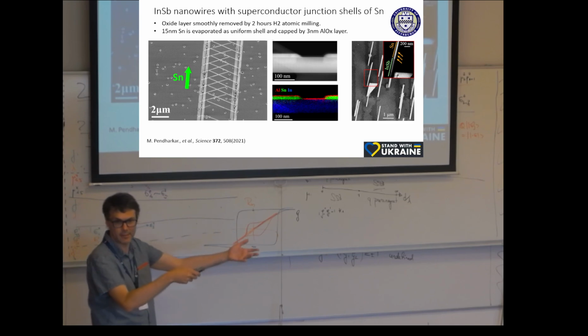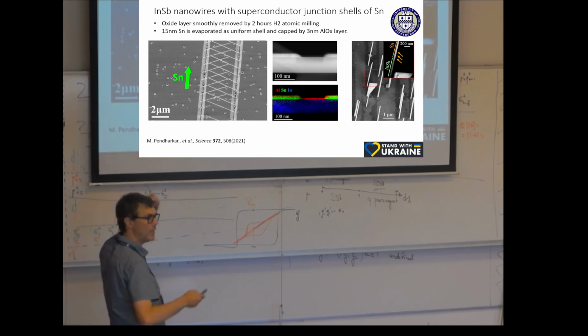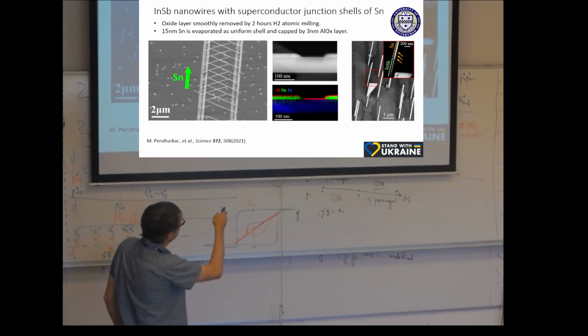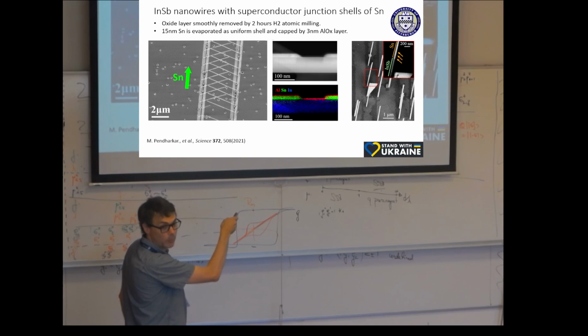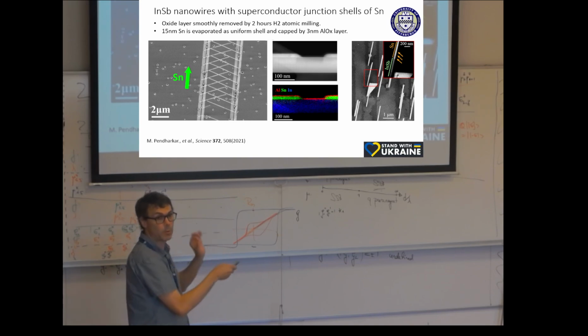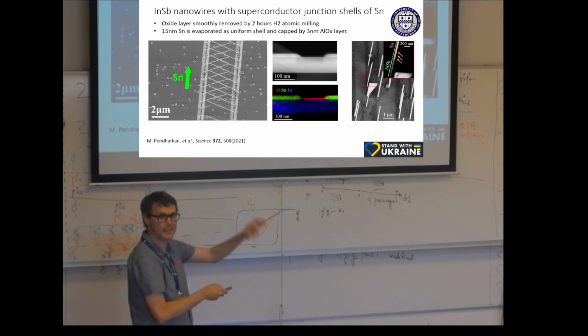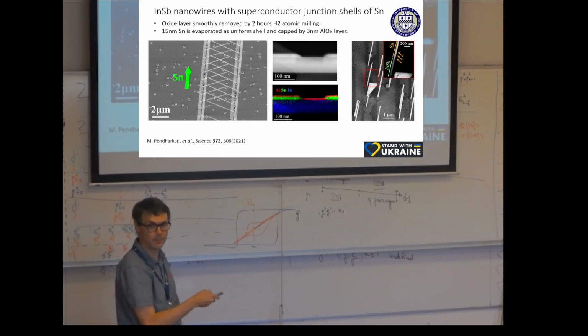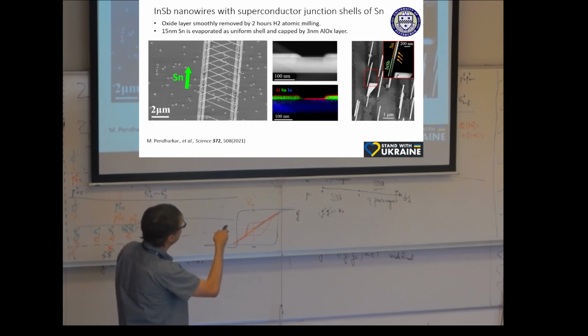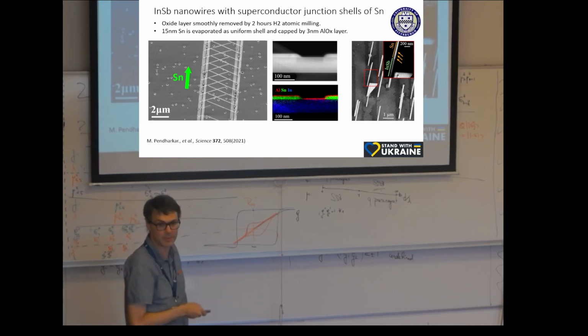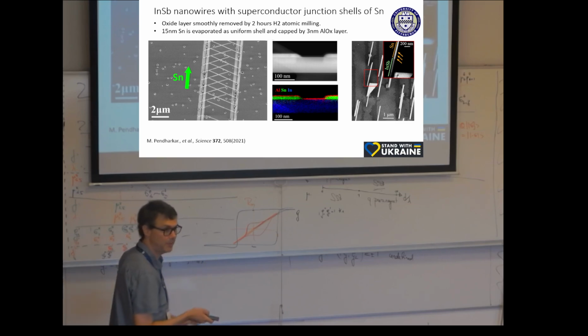Why all this? Why all this crazy effort? So that we could have as pristine as possible an interface here, without any scattering, and without processing, without putting in acids and solvents and other things that damage the crystal. This interface is very, very transparent. This wire is ballistic. Electrons travel from here to here without scattering, other than specular reflections perhaps. And there are no crystalline defects here.